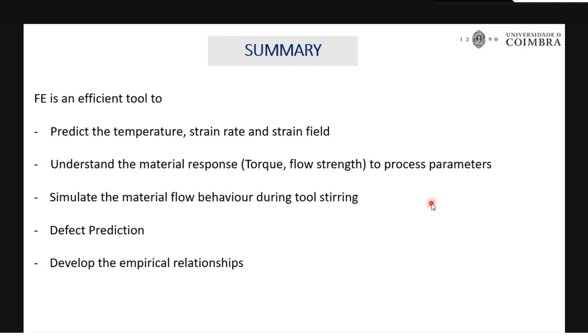So the summary is like FE is an efficient tool to predict the temperature, strain rate, and strain field, which I showed in my results, and we can understand the material response. In this way, if you know how the material responds, you can overcome the problem of defect formation and tool failure. You can reduce the cost involved in achieving the optimized joint. And with the FE, you can develop the empirical relationship with virtual material constants. You can play with the material constants by changing different parameters, so you can find what are the actual parameters influencing the friction stir welding.